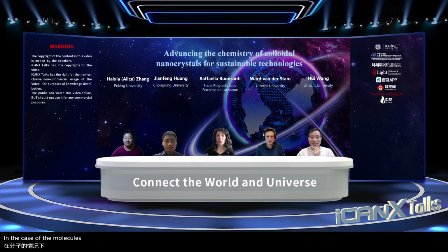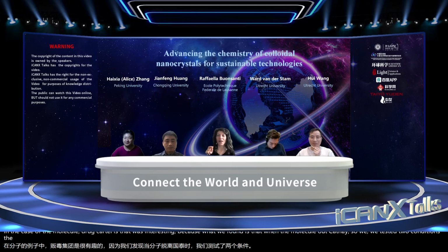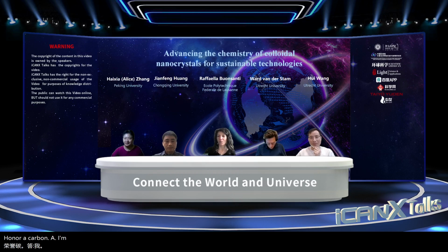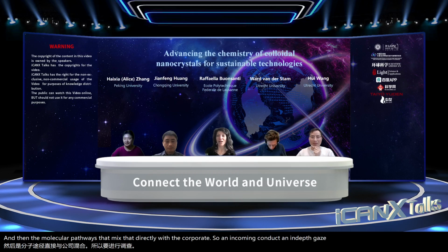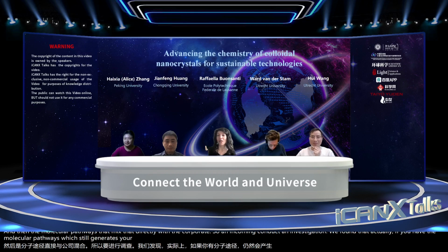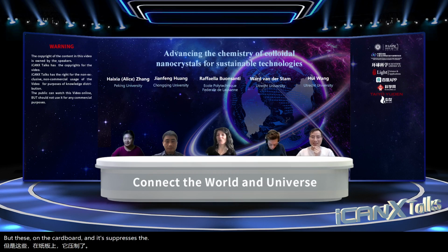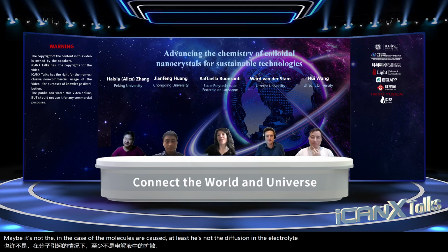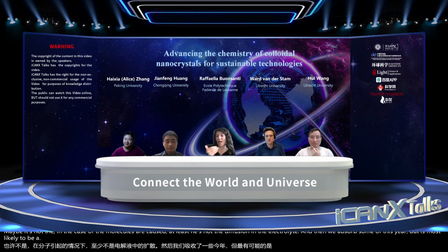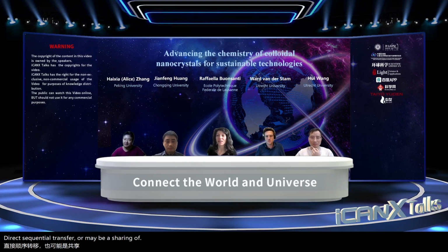In the case of the molecular catalyst it was interesting, because we tested two conditions: the molecular catalyst on carbon particles, mixed with the copper cubes, and the molecular catalyst mixed directly with the copper cube, so an intimate contact. In that case, we found that if you have the molecular catalyst, which still generates CO, on the carbon, it suppresses the C2 products. This suggests that in the case of the molecular catalyst it is not a diffusion in the electrolyte and then reabsorption of the CO, but most likely a direct sequential transfer, or maybe a sharing of intermediates. But of course, we don't have much knowledge of the actual surface chemistry that is happening.